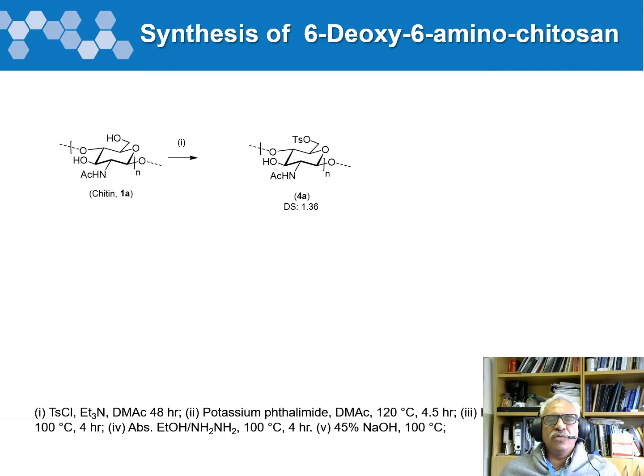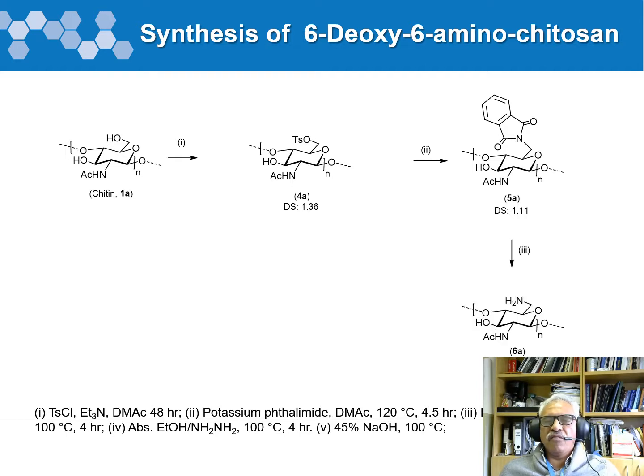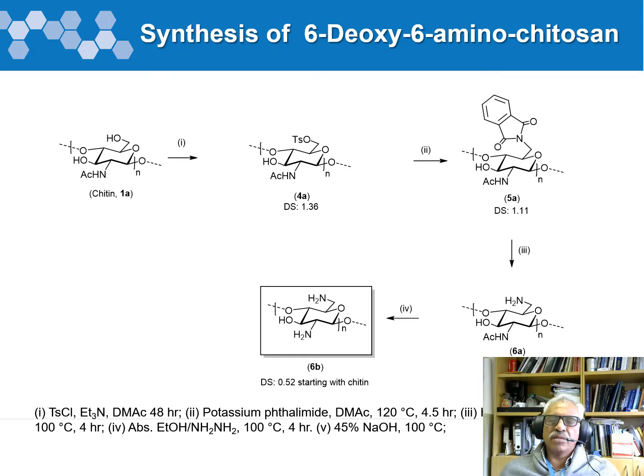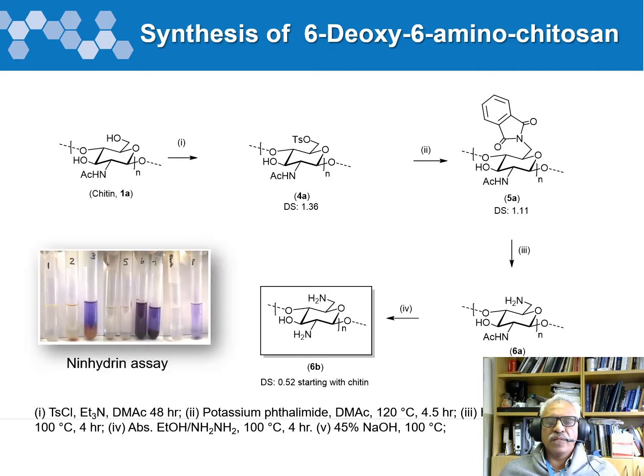Of course, you can do this with chitin itself, get good substitution, and then you can substitute the tosyl with phthalimide, and then deprotect, and you have aminochitin, which is much more water soluble than chitin itself, and then of course you deprotect by base treatment, and you get your product. And of course, we can follow this transformation with ninhydrin stains the polymer quite clearly.